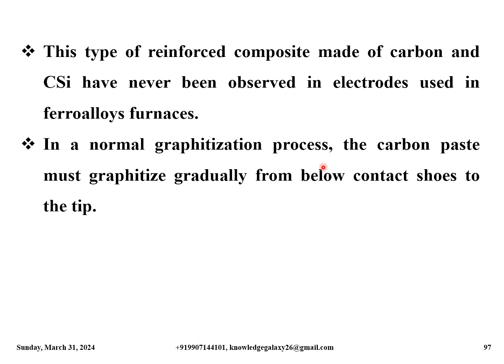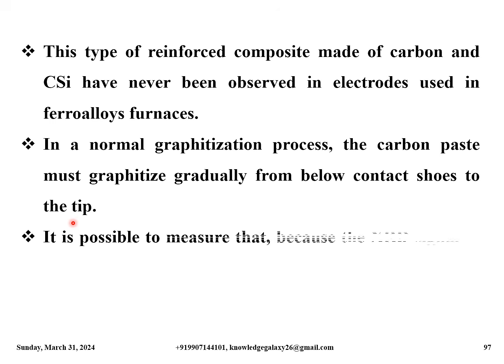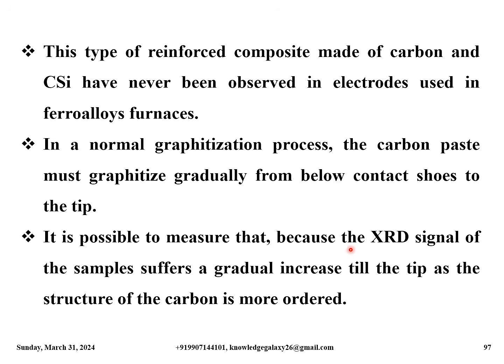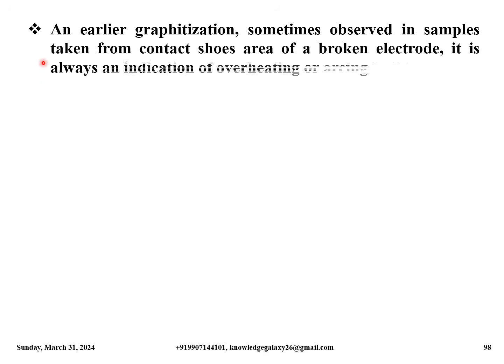In a normal graphitization process, the carbon paste must graphitize gradually from below the contact shoes to the tip. It is possible to measure that because the XRD signal of the samples shows a gradual increase till the tip, as the structure of the carbon is more ordered. An earlier graphitization is sometimes observed in samples taken from the contact shoes area of a broken electrode. It is always an indication of overheating or arcing in this area.